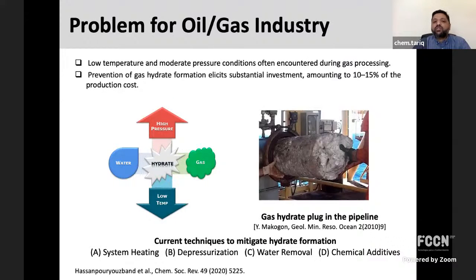Hydrate formation is a very big problem for the oil and gas industry, because for gas processing you are always going to deeper sea now. There the ideal conditions for hydrate formation exist. As you go deeper into the sea, you have low temperature and high pressure, and whenever you are processing the gas, you always have some produced water available. Whenever all these conditions are met, hydrates start to form and sometimes can clog the whole pipelines, which can cause disruption in production, and sometimes can be fatal for life. That's why industries are spending sometimes 10 to 15% of the production cost, which can run into millions of dollars.